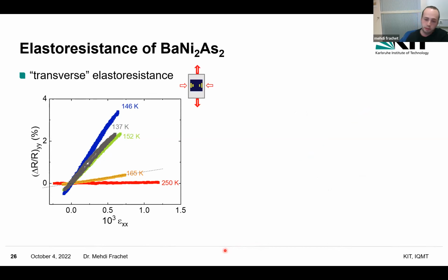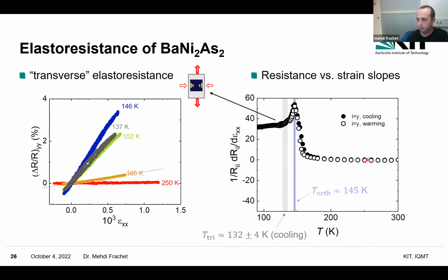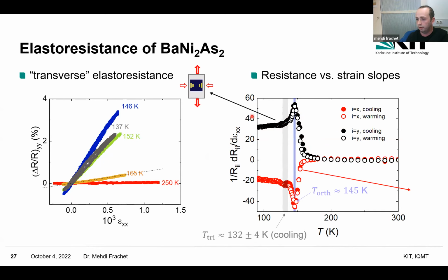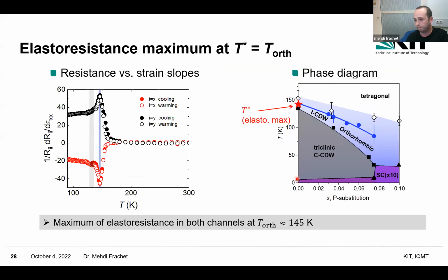What we usually do in this kind of experiment is just take the slope of this resistance versus strain variation. This is what is plotted on the right side as a function of temperature. We measure this upon cooling and warming, and you see that there is not so much difference between cooling and warming measurements. Same quantity, but in the longitudinal geometry, so measuring the resistance along the pulling direction, and you see the same effect, but with an opposite sign. So just to summarize quickly, we have a maximum of elastoresistance in both channels, transverse and longitudinal, at this 145 Kelvin temperature.